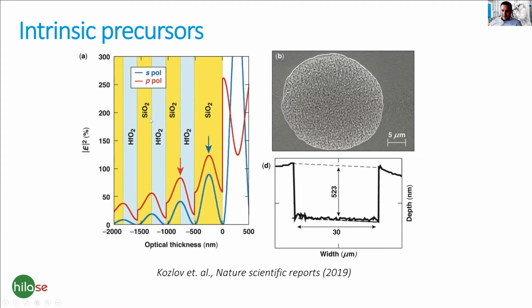Because again, if you have a small piece of dust, for example, in this multilayer, then on this small piece of dust you will see again this E field enhancement, which is proportional to the difference of the refractive index of these two media.